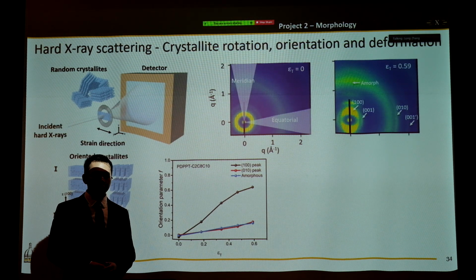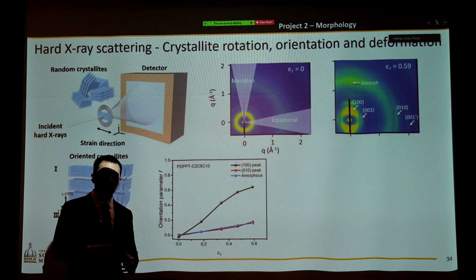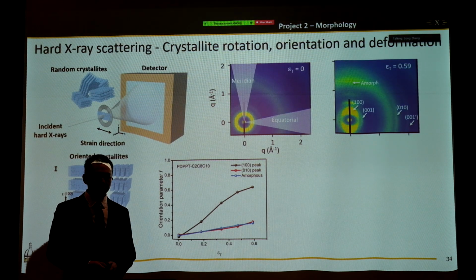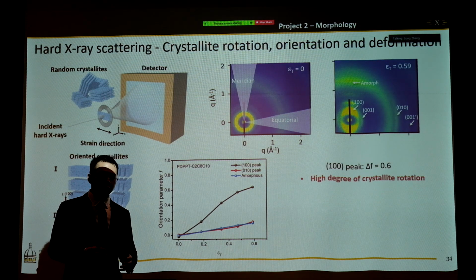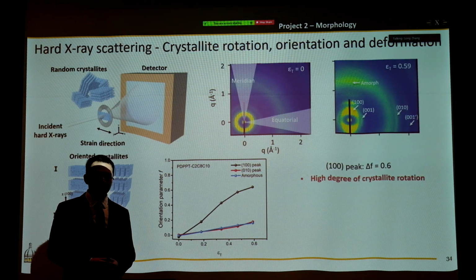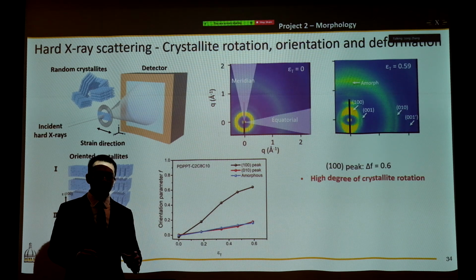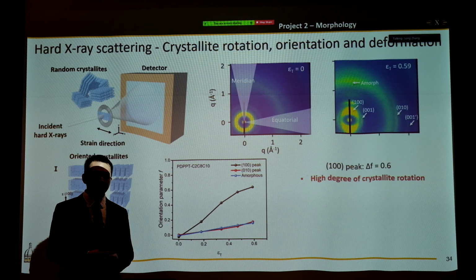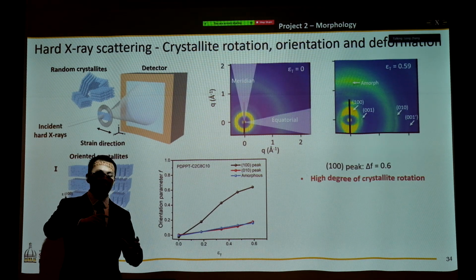And shown on the bottom left are 4 types of crystallites that we think will exist in the thin film. And more importantly, let's take a look at the orientation parameter evolution upon strain. As we talked about, the 100 peak is the lamellar rotation peak, and the delta F value reaches 0.6 after strain, which means this rotation phenomenon is very efficient in these polymer thin films. And that is understandable because your crystallites are aligned along the strain direction.